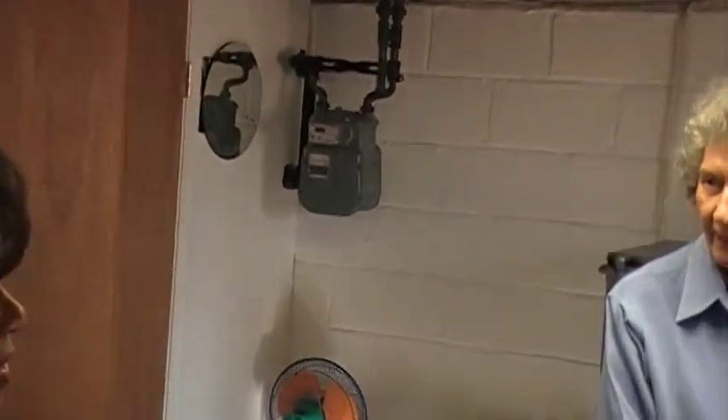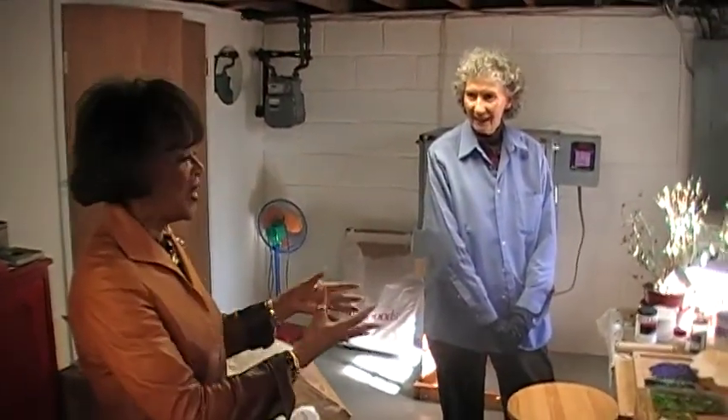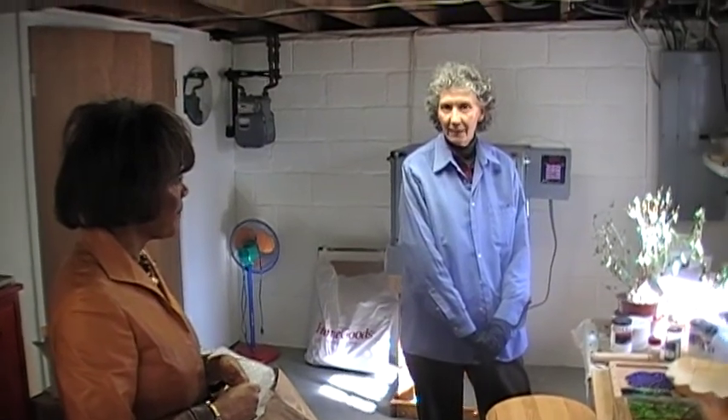One of the things I know that people have been asked about glass artists is the fact that the temperatures are very hot while you're working with these things. So when that comes out of the kiln, how long is it before you can start to work with it? It's a long time. Cooling glass is a technique called annealing, and you have to control the cooling. This kiln, when I cool the glass, I set the rate at which I want it to cool. If I have something an inch thick, I'm going to have to cool it for about 24 hours, very slowly in the beginning, and then slightly quicker later on.